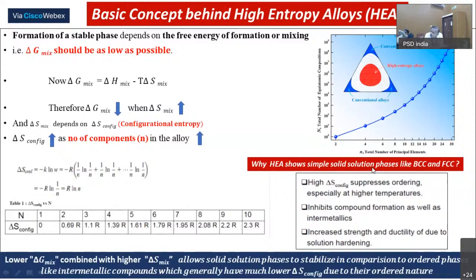So another concept popped in: the same reduction in free energy can be obtained by increasing the entropy. Now, how much? That is the question that comes in. The table shown below shows that as you increase the number of components, the configurational entropy increases. The typical high entropy alloys are those where the entropy crosses 1.5 R. So all the alloys which form a single phase by adding 5 elements classify as high entropy alloys.